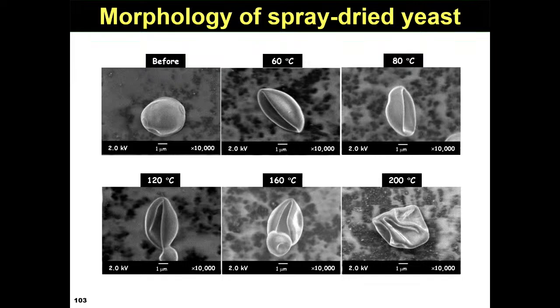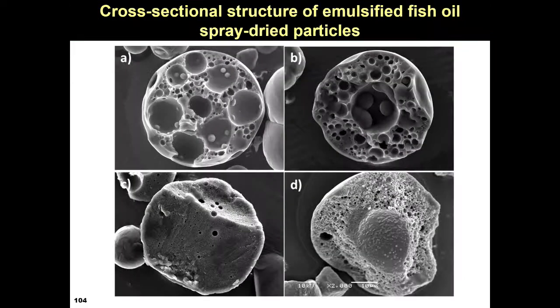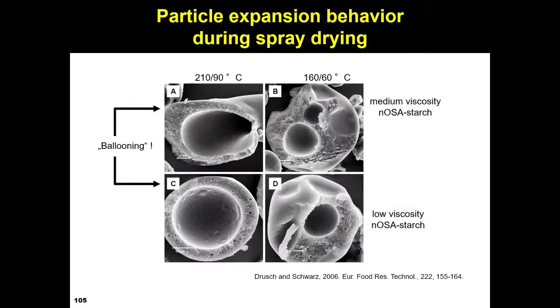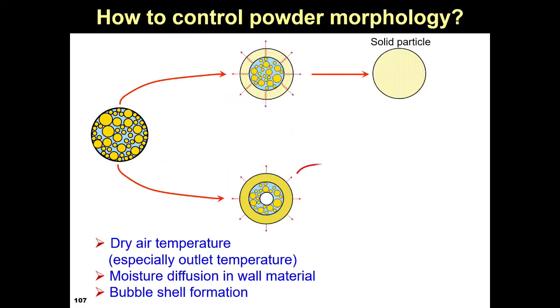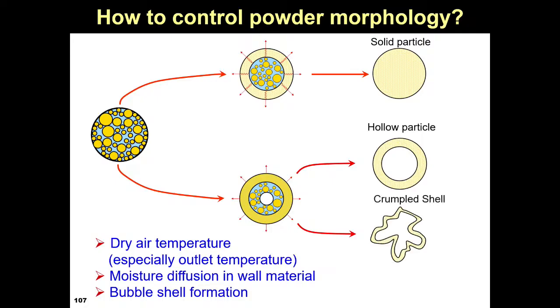This is the yeast spray dryer shape, and this is another type. So, drying condition, and then also raw material, and then film formation rate affect the morphology of the spray dried powder. And then morphology of powder affects the stability of the core material in the powder.